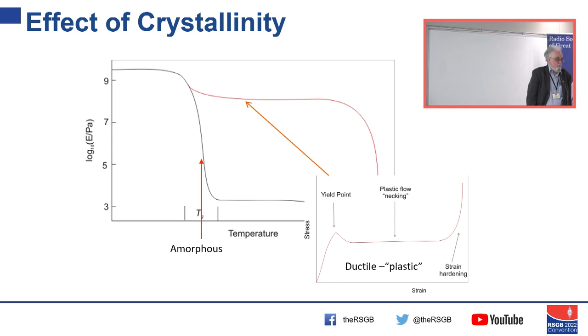It has a yield point, and then it flows. It stretches and stretches and stretches. Sometimes you can get elongations to break of 300-400% before the material snaps. And often what happens at the end of the process is that it hardens, and then it snaps. So this semi-crystallinity is extremely valuable because it gives us this property of mechanical toughness.